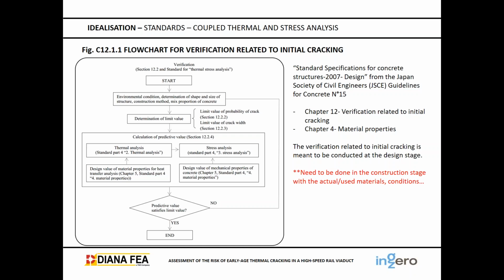Okay, in the flow chart they propose, we have to start with the environmental conditions, then determine the shape and size of the structure, the construction method, the mix proportion of the concrete, determine the limit value, and calculate the predicted value. We are doing this, but in the upward direction instead of downward. So we have the facts and, by studying these things, we have to arrive at a value and determine whether they are going to be worse or whether it's not a matter of concern. Okay, so for the thermal analysis and the stress analysis, we need all the material properties for heat transfer analysis and the mechanical properties of the concrete.